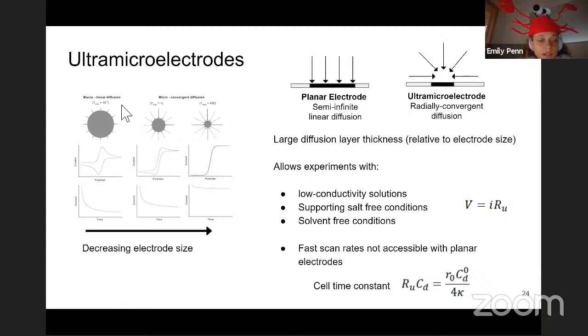So in this plot on the left, in the first column, we see what we would see if we have a large planar electrode. This would be semi-infinite linear diffusion. We get this duck-shaped curve like we've just walked through in the previous section. As we decrease the size of the electrode, we're going from this planar semi-infinite linear diffusion to a radially convergent diffusion once our electrode gets really small. So instead of seeing these peaks, we just see a steady state sigmoidal curve.